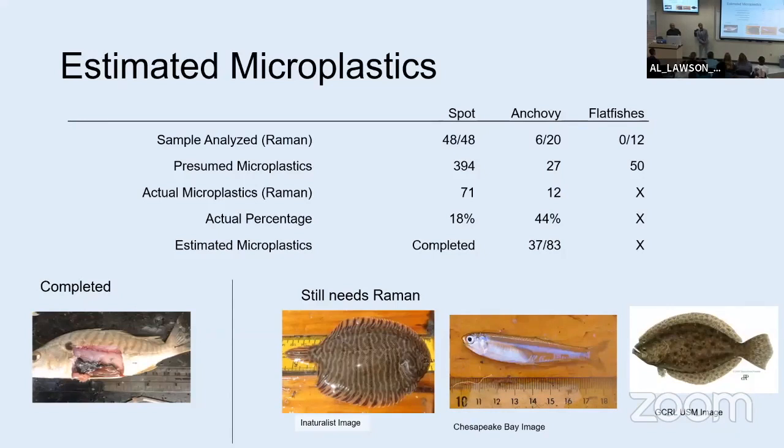That is a great question. A lot of these plastics are hypothesized to be secondary, so they're not exactly pristine from the manufacturer they originated from. A lot of the time they're biodegraded, and that's what makes the Raman spectrum matches different. That's why the example I showed previously had 97%, while some were 75% and some 85%.